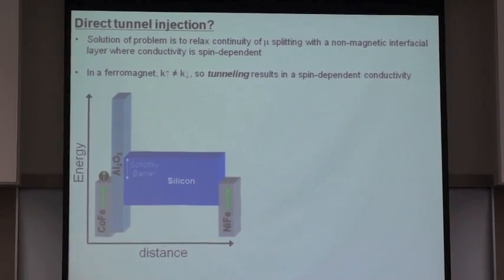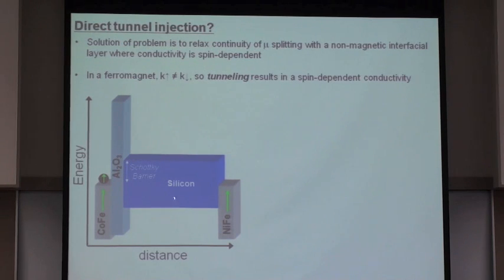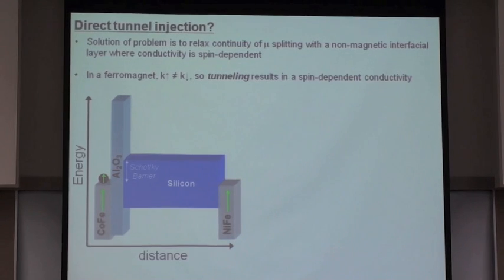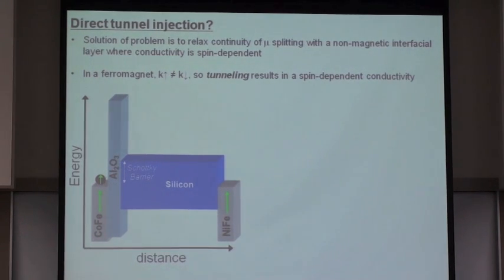The problem here is that if the semiconductor itself is very lightly doped, or even undoped, as I'll show you, there's no way to actually efficiently inject even charge. And the reason why is due to the discontinuity between the Fermi energy and the conduction band of the semiconductor. Now you might say, well, this is trivial. We can get electrons from the Fermi level of the ferromagnet into the conduction band of the semiconductor just by applying voltage. Then this Fermi level will rise because you're giving potential energy to the electrons, and then you'll get tunneling into the conduction band.